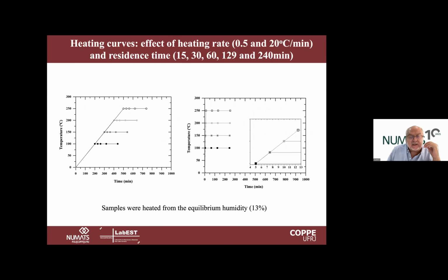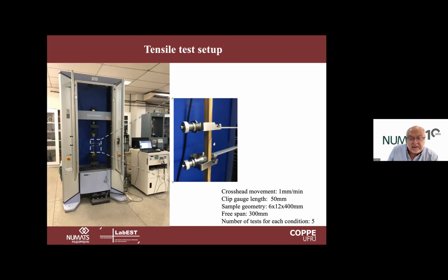So what we did here was to take some of these strips and put them in an oven. Samples were all in equilibrium humidity when we started, so humidity wasn't a variable. And we did different residence times and different temperatures, from 100 C, 150, 200, and 250 C, to see the response of these materials when we increase the load and also the residence time. And then we did the test afterward in a 300 millimeter frame using a clip gauge to detect the extension and calculate the elastic modulus as well.